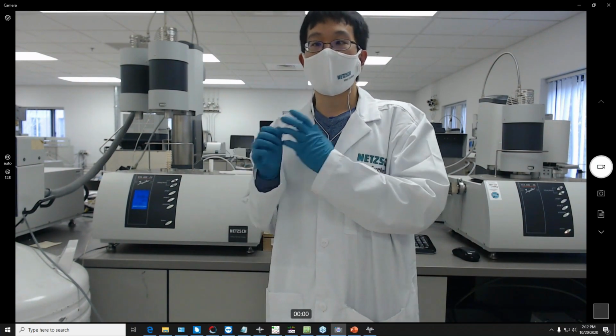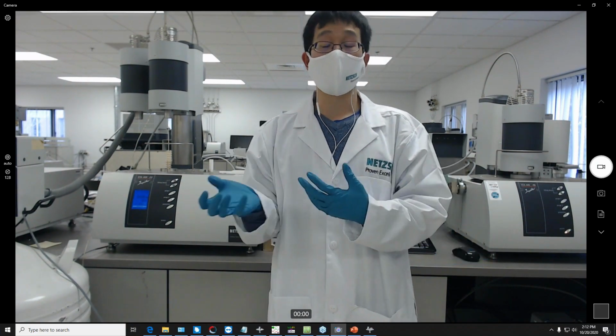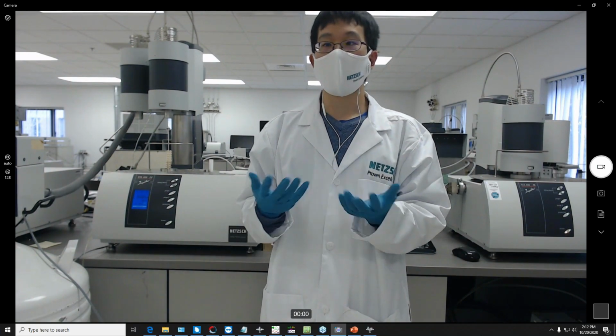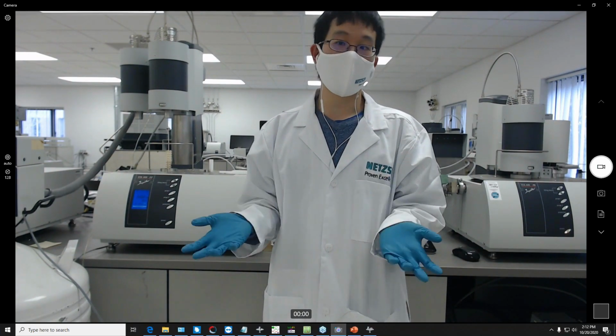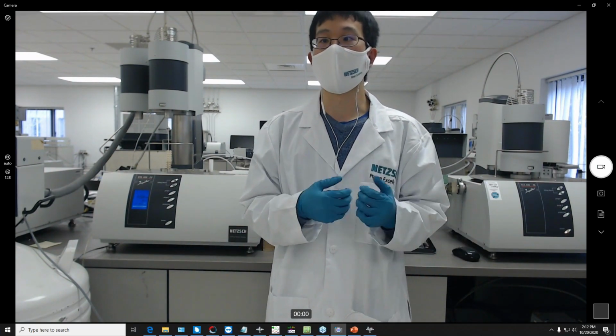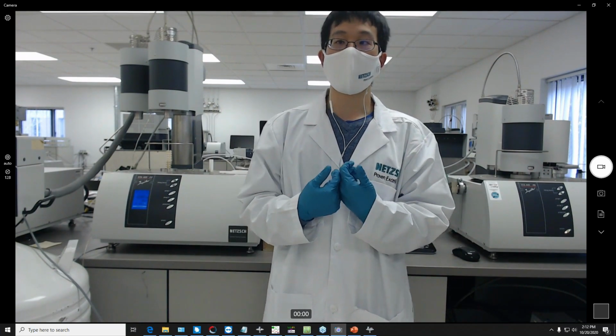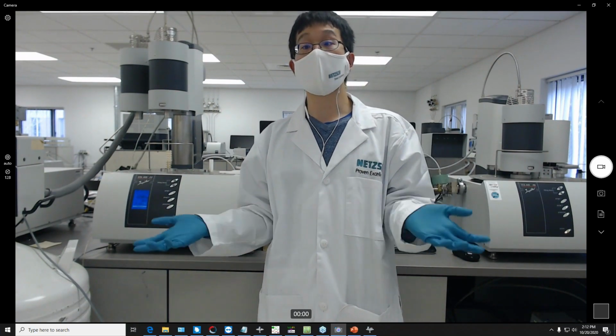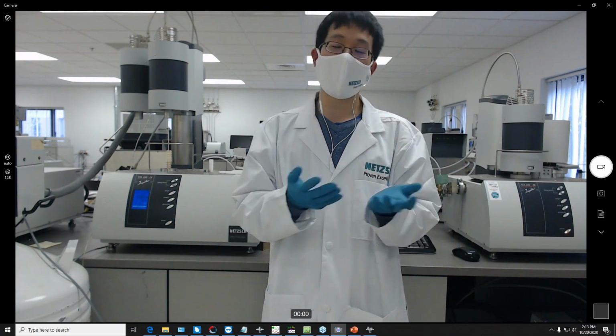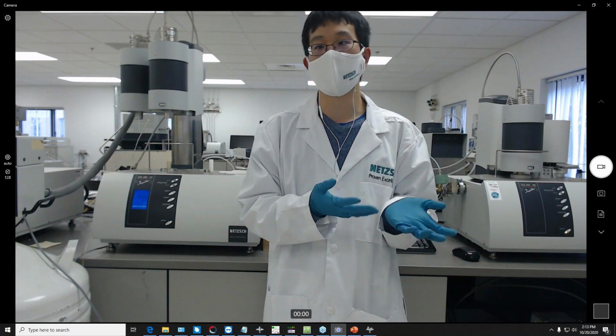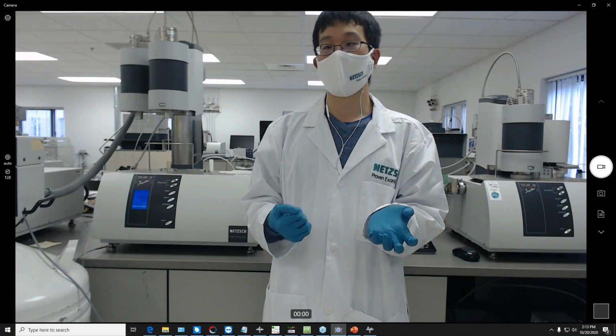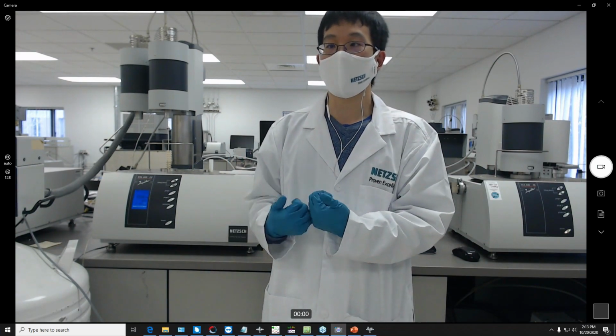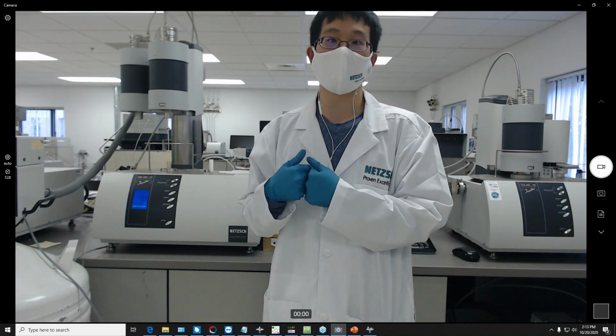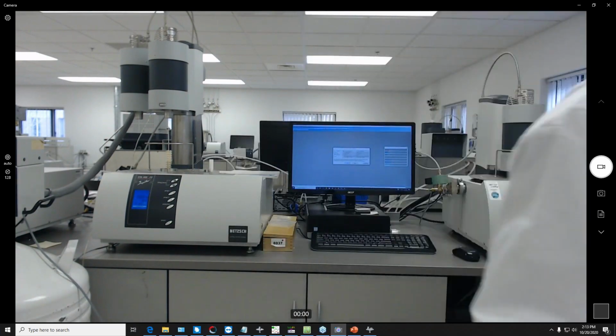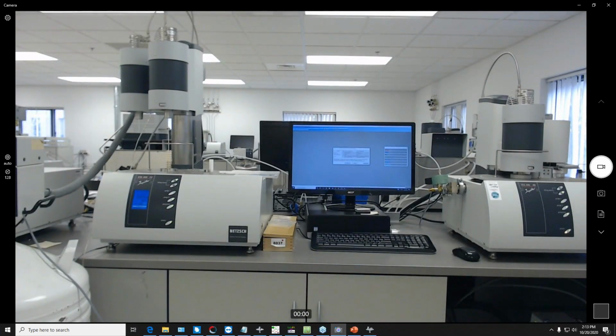Now, if I wanted to run a sample measurement to 500 degrees Celsius, all three of these would be acceptable because they all are within the allotted temperature range. But if I wanted to run my measurement to 1200 Celsius, well, then I can't use aluminum because aluminum will melt at 660. So then my choices are ones that can hit those particular temperatures. And so let me go back on the computer screen again real quick.